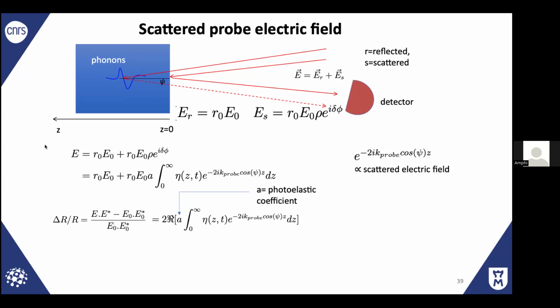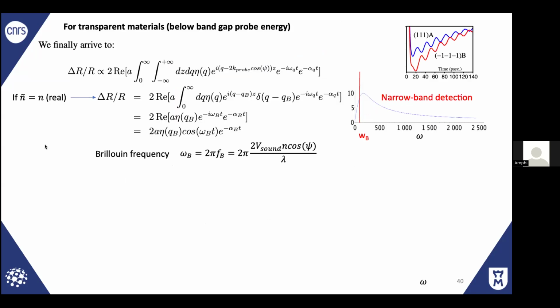And you have to make an integral. Since the phonon can be here or here or here, you have to integrate over z from 0 to infinity. So this is what you can get. And if you are interested in the reflectivity, you have to take just the real part. This is the integral that characterizes the detection. If this strain can be developed in Fourier space, then from the optical point of view, you finally get such an integral to be solved.